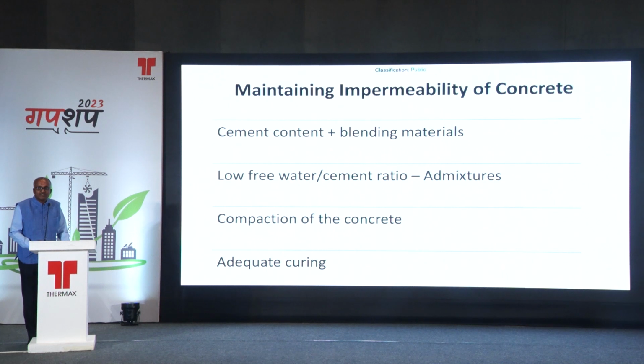Of course, admixtures have to be used wherever needed, and they have to be used in a way that is compatible with the type of cement. So a sufficient number of trials is required. While we interact with customers of various segments, we have seen that the trials have been done once in a month, or are not being done frequently. But what is to be done is that it has to be done frequently to check the compatibility of cement and admixture, compaction of the concrete, and adequate curing.